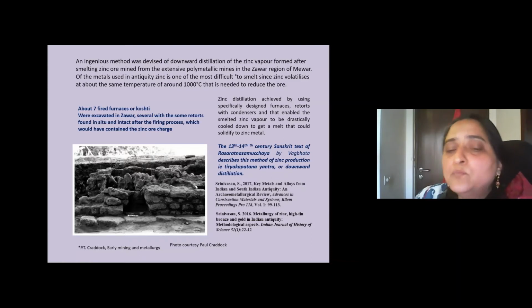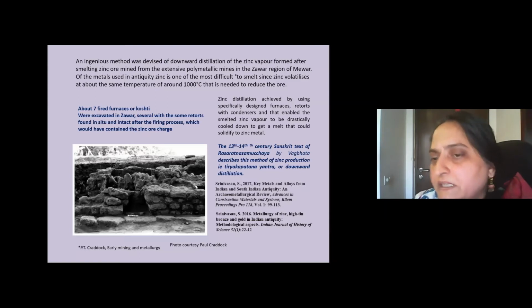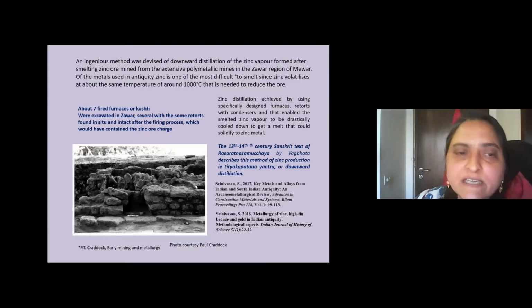And what was actually done here in Zawar, which was quite a distinctive process, was the distillation, whereby they used this downward distillation technique. And this was achieved by using specially designed furnaces and retorts with condensers and so on, so that it enabled the smelted zinc vapor to be very drastically cooled down to get a melt that could be solidified into zinc metal.